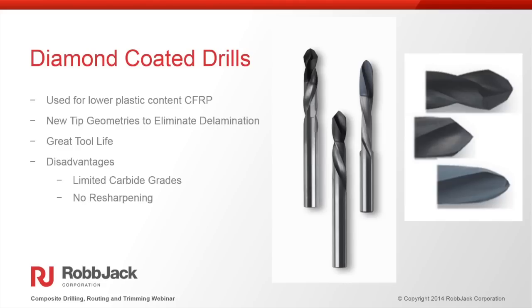And so you can see this top tool in this area over here, we have an 8-facet tip, and that 8-facet tip, when you pierce through the material, you'll get a little bit of delamination, and then the double angle there will ream out the hole as you finish the hole to get rid of that uncut fibers, delamination. The middle tool here is more like a traditional 4-facet single angle, and it works with a lot of composite materials, but as you get into the more exotic materials, sometimes you need different angles to help get those clean holes that you need.